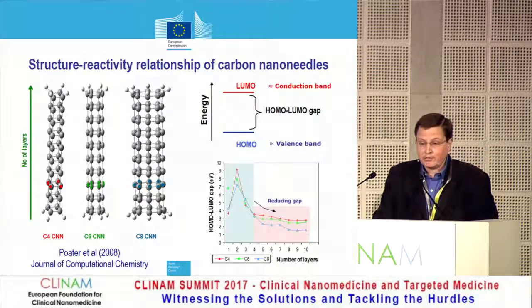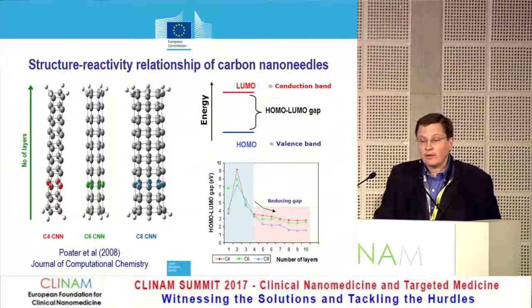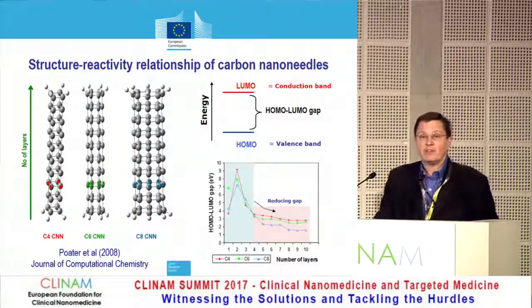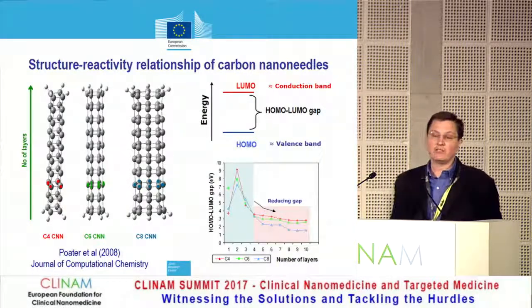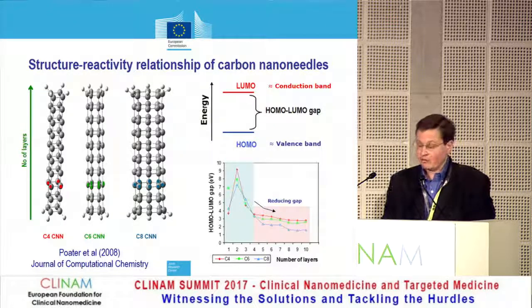on the reactivity. So you can see that as the nanoneedles are actually made to be longer, the gap between the HOMO energy level and the LUMO energy level actually decreases. So in a sense, the nanoneedles become less stable, more conducting, more reactive as they become longer. So here's a simple example of a structure-activity relationship based upon mechanistic reasoning.